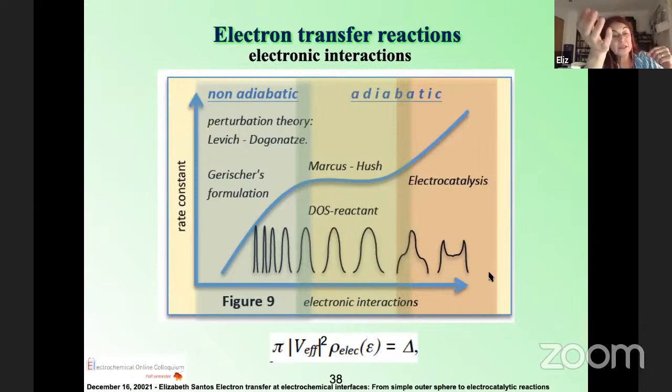If we have a molecule with atoms involving different orbitals, the overlap with the metal is different, and depending on the metal, how long is the extension of the orbital from the surface, all these parts are involved in order to obtain this term here, yes, this integral that gives the interaction between the electronic levels of both systems.